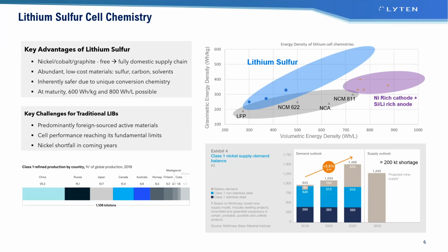People talk about 1200 watt hours per kilo. I think you better cut it in half for any practical reality. So, a real practical roadmap says you should be able to get to 500, 600 watt hours per kilo. Okay. Volumetric, never as good as conventional lithium ion. This is really a cell that's lighter weight. Okay. So its big benefit is the gravimetric energy density to weight.